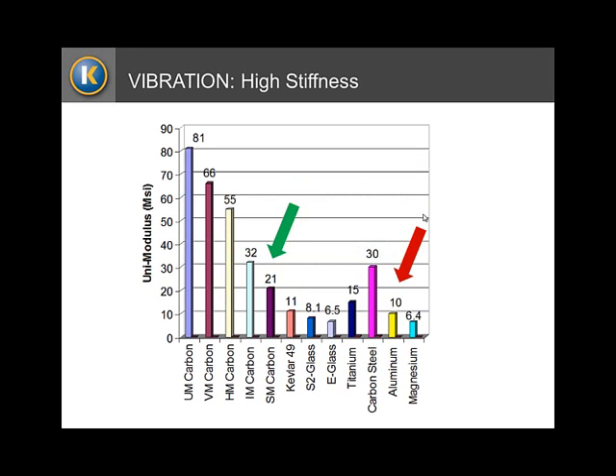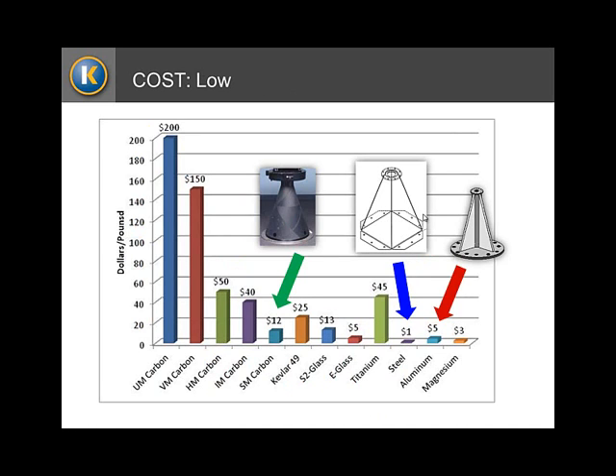It's also about its performance in terms of stiffness. Now, stiffness is the modulus of elasticity of the material, how much it stretches or doesn't stretch under load. And that, for the aluminum, is around 10 MSI, millions of pounds per square inch, whereas for standard modulus carbon, you get double that. And look at E-glass. E-glass is less than the aluminum. So you see, by using different grades of material, you can go from a very low modulus to a high modulus, which makes it stiffer, deflecting less under load, which is important for vibration.